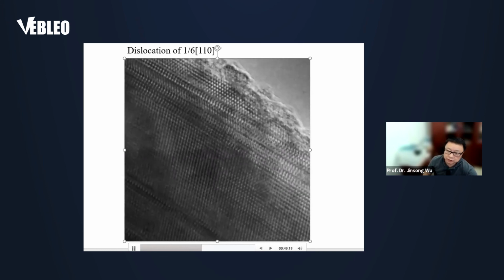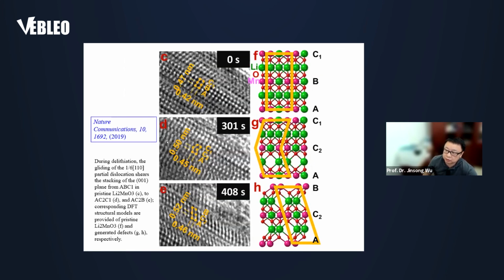And you see there are a lot of changes here, especially if we take out the snapshots of the same area and look carefully at these high resolution images. Here at 0 second, we call it the 0 second as the starting point, the stacking of the 001 planes is A, B, C1. And such a stacking sequence became AC2C1 at 301 seconds. And at 408 seconds, it becomes AC2B. Which means that there is a 1/6 of 110 dislocation gliding. We call it dislocation gliding through here. So it changes the stacking of the layers of the 001 layers.